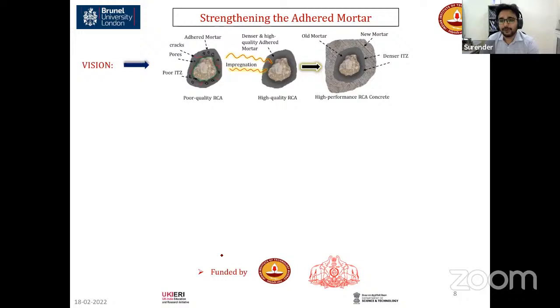The second thing is that, let's say after you get the aggregates from crushing, we are focusing on addressing the existing issue with the adhered mortar. You might know that the issue with the adhered mortar is that it is highly porous. You might see some cracks in the existing mortar, and the interfacial transition zone between the aggregate and old mortar will be very, very poor.